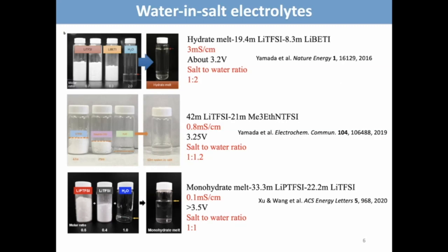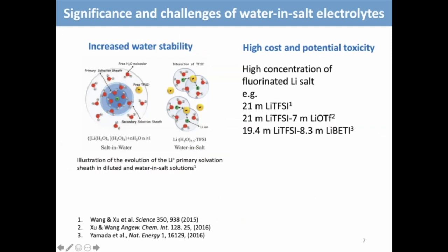So water-in-salt electrolyte has been widely applied, with many subsequent efforts in the field, including hydrate melt using about 20 molarity of lithium TFSI, or 42 molarity lithium TFSI, or 33 molarity LiPTFSI. These highly concentrated electrolytes are effective in increasing water stability, as we see that they provide a wider stability window compared to pure water. However, they are also facing high cost and potential toxicity issues for future application in terms of commercialization and also sustainability.